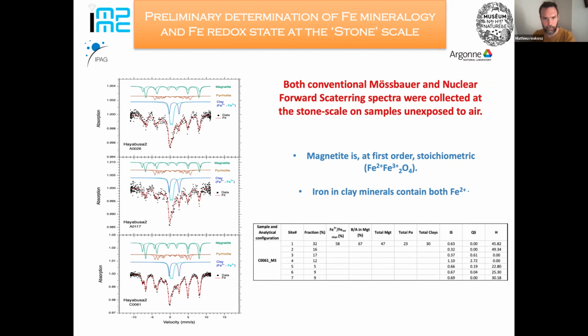With this model, and so you can see the parameters in the table, with this model in hand, we fit the other spectra that are not as good. So clearly we cannot derive a very robust and univocal fit to the data for A26 and A117.